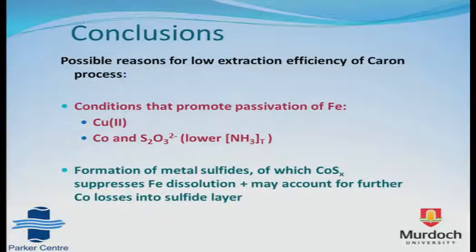So in conclusion, to summarise my results, the main findings have been that there are certain conditions which can promote the passivation of iron, one being the presence of even very low amounts of dissolved copper, and the presence of both cobalt and thiosulfate, although this takes place at a somewhat lower concentration of ammonia. And more importantly, the formation of metal sulfides, of which the cobalt sulfide appears to suppress the iron dissolution, as well as promoting passivation, as already mentioned, and may in itself, regardless of whether passivation takes place, account for further losses of cobalt simply into this layer.